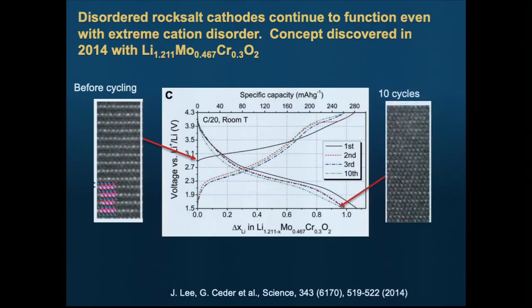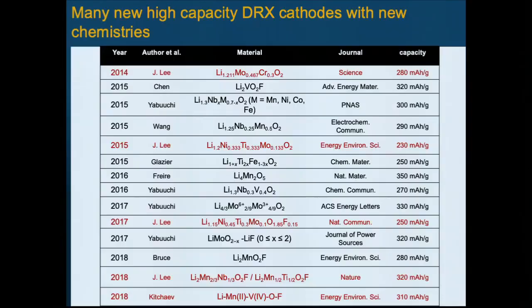This is 10 cycles. This is a fully disordered rock salt. But the remarkable thing is after 10 cycles, that's the green line here, we still have full capacity in this material. So this was the first proof of concept that you could actually make a disordered rock salt that had really good lithium transport and lithium percolation.